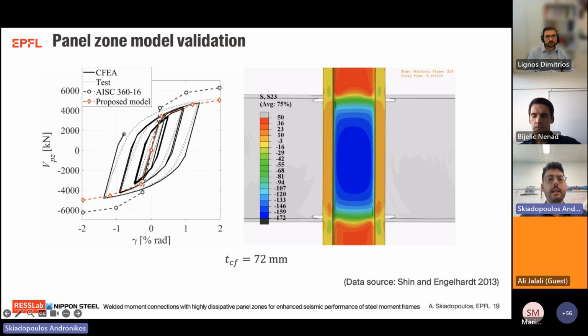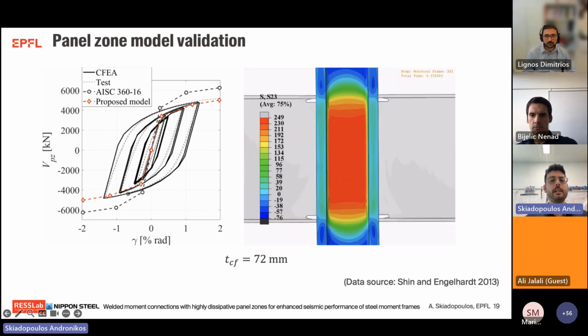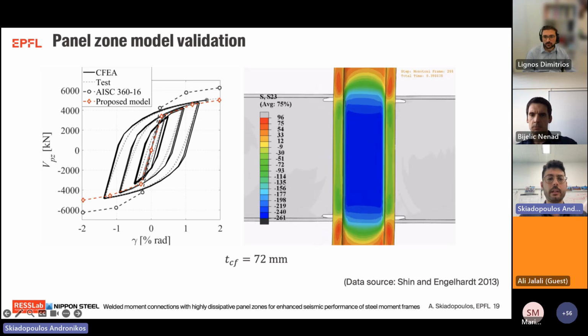What we see in this slide is that the proposed model is capable of predicting very accurately the panel zone elastic stiffness, as well as the panel zone shear strength, regardless of the panel zone shear distortions. So what we can conclude from this slide indicatively is that these results show us that we can potentially rely on panel zone designs that are up to 6 gamma y at least.